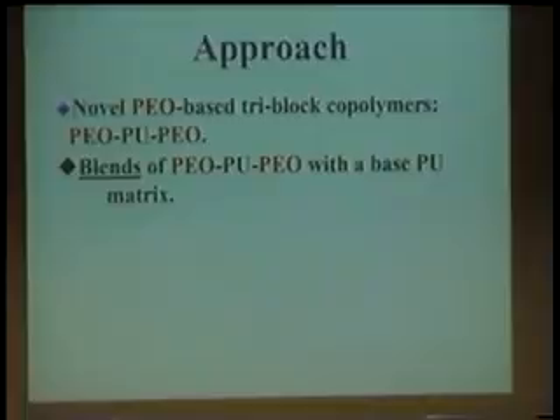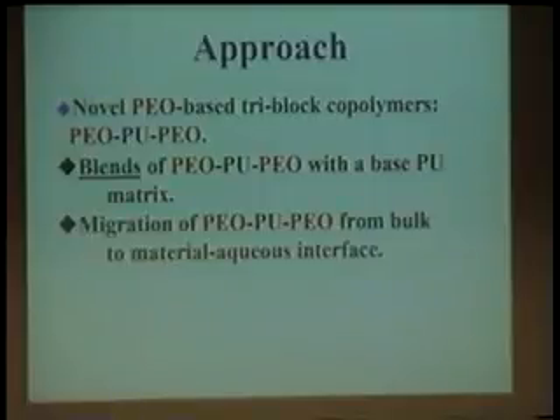And then what we do is we blend those copolymers into a base polyurethane, which is then a matrix for the overall material. And the important point, too, is that the polyurethane in the middle block of this copolymer has a structure very similar to the matrix polyurethane. So that has implications as well. And so we expect that if we put this blend now in contact with an aqueous system, since the PEO is hydrophilic, the copolymer will migrate to the surface and will give us our anti-fouling effect, our protein resistance effect.